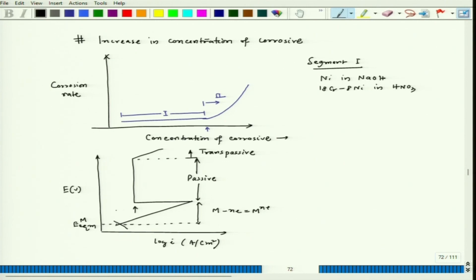This particular current density corresponds to Ip, which is the lowest current in that particular anodic part. Of course, if I try to see the interaction with the cathodic reaction, then this can sometimes be the lowest current density. For example, if the cathodic part interacts here, then this corresponds to IC. So, then this becomes I corr.